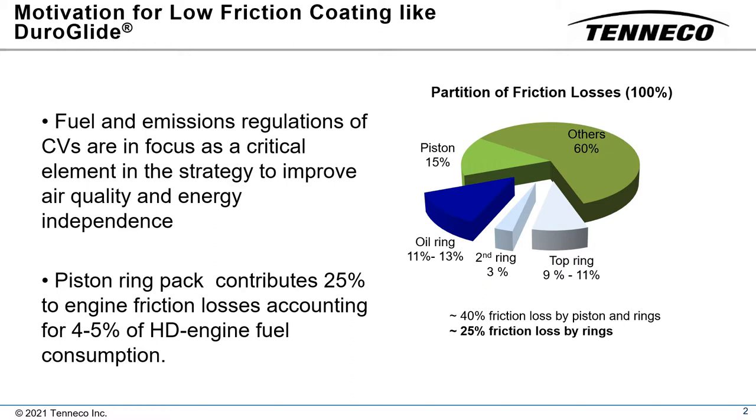In addition, alternate fuels used in medium-duty and heavy-duty engines have created new challenges for upper compression rings. For example, natural gas fuel with an inherently poor lubricity induces tribological scenarios that many ring materials have difficulty supporting. Upper compression ring materials must be able to survive under borderline mixed lubrication conditions without wearing significantly and without scuffing.